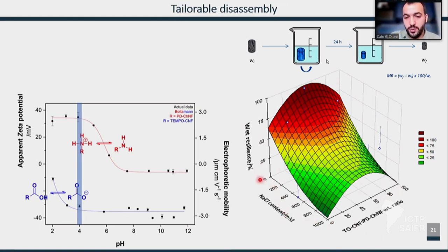But when we do it with low ionic strength, still, if you have only a little bit of one charged species, the wet resilience is going to be higher. As we go up in ionic strength, then we get rid even of the strongest complexes, right? So it's really electrostatically driven, I mean, entropically driven, but not Coulombic, this is what I mean, but really dependent on ionic strength and pH.